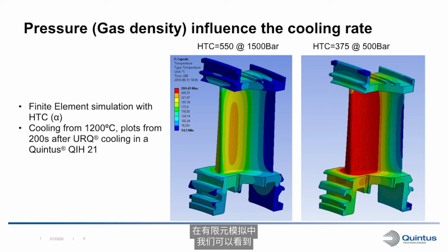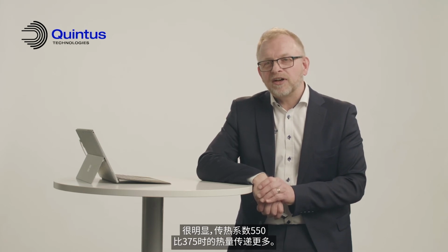So in the finite element simulations, we can actually look at specific parts from CAD drawings that you can supply us and actually look at the real cooling in the part for you. And in these two plots, you can see the 1200 C plots for 200 seconds at different pressures. So obviously with the heat transfer coefficient of 550, you get more heat transfer than you do at 375. So running at higher pressure has a benefit to heat transfer. It means you can also cool the parts quicker.